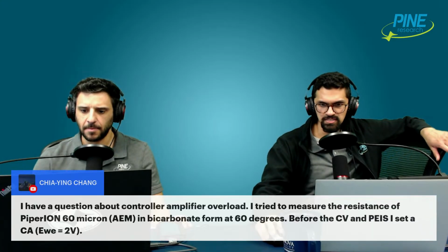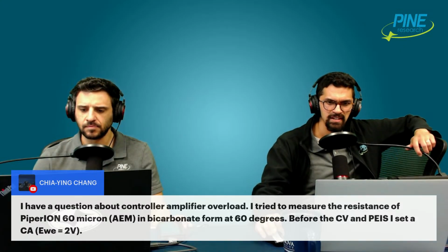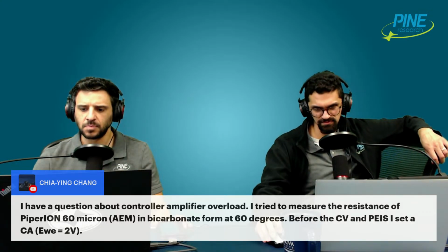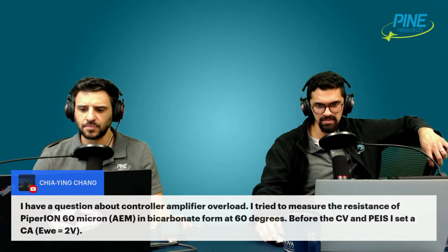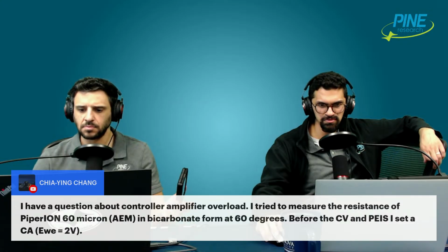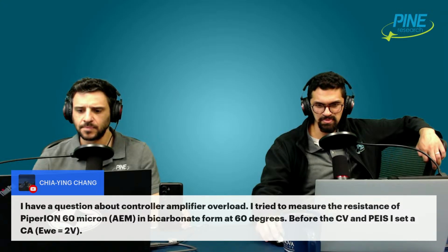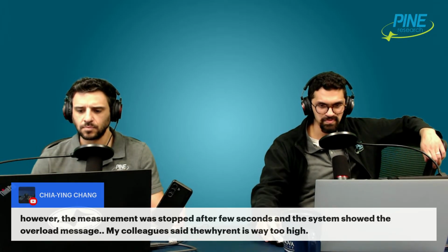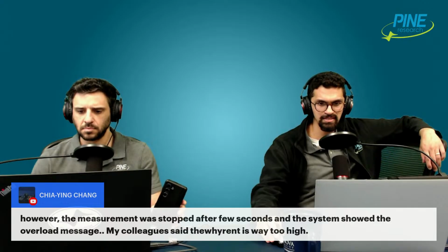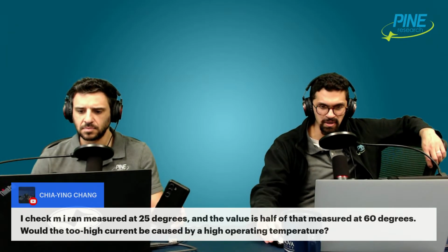All right, we have a series of questions from Chaying Chang. I have a question about controller amplifier overload. I tried to measure the resistance of PiperION 60 micron AEM anion-exchange membrane in bicarbonate form at 60 degrees. Before the CV and potentiostatic EIS, I set a chronoamperometry of the working electrode to 2 volts. However, the measurement was stopped after a few seconds, and the system showed me the overload message. My colleague said the current was way too high.